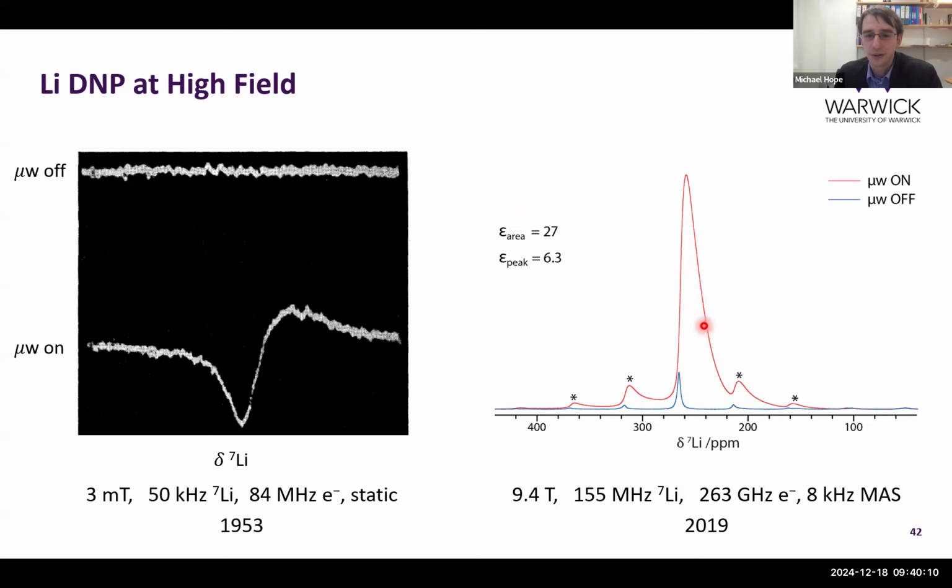I realize that we've been talking about lots of different tails this talk, but this is for a different reason. So I mentioned that the Knight shift is due to coupling of our nuclear spin with the unpaired electrons in the metal. I also said in order to do Overhauser DNP, we need to saturate our electron transition in order to drive that cross-relaxation. And so this reduction in the Knight shift is actually due to the partial saturation of the ESR transition.